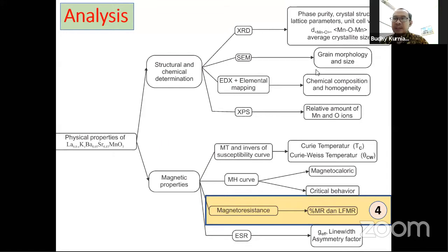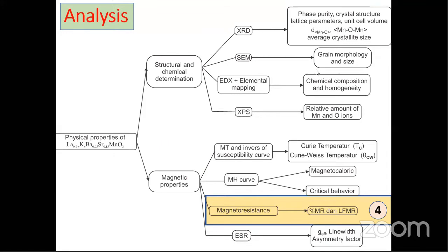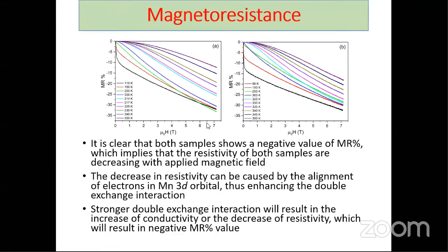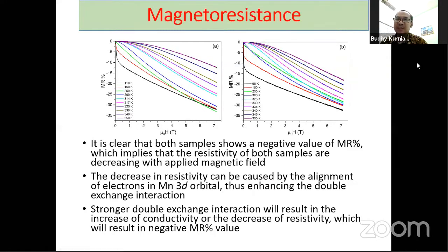The other analysis is for the magnetoresistance. In this experiment, we have a direct method to measure the magnetoresistance. The indirect method is to measure the resistivity versus temperature, and after that measure the resistivity versus temperature under the influence of the magnetic field. But in this experiment, we get the direct magnetoresistance curve.